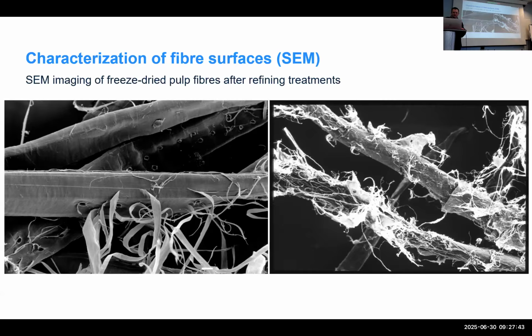These are freeze-dried fibers we're looking at in the SEM after various treatments. And you're now already experts in fiber morphology. We've exposed the S2 wall here, and we can see a very small fibril angle. This is a nice, straight fiber, would have pretty good tensile strength, I would imagine. But here we can see mechanical treatments peeling strips of that S2 wall layer. And it's interesting, as Ben said in the seminar, because these are small, your electron beam is going to go through some of these. So it's almost transparent right here,